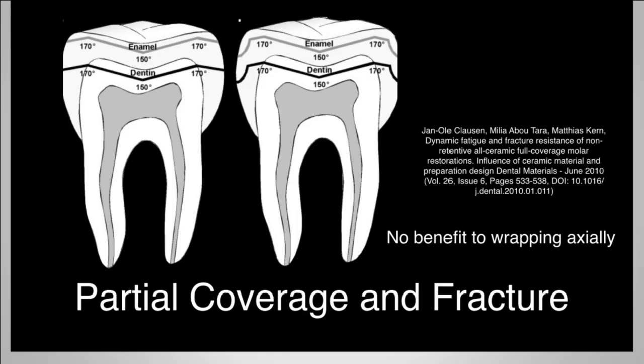What we see today, and what this paper is showing us, is that if we bond glass-based restorations across the occlusal surface with no axial preparation, and that's what the far left-hand side is depicting. In the middle of your screen, you can see there is an axial prep. We bond something with an axial prep. Both cases are bonded. We put pressure on each of those teeth until they break. We see that there's no difference. They break at the same level. With bonded ceramics today, the entire occlusal table is bonded across, and it does not need traditional ferrule as we think about it. We do not need to surround the tooth as we once did.